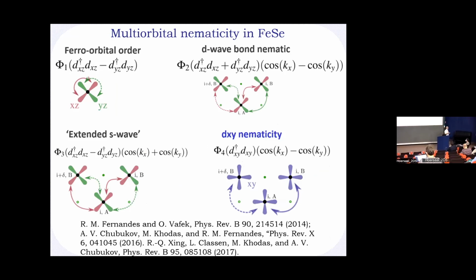Now, it turns out that in order to describe it, of course, you always break a B1G symmetry, but you actually need a combination of the nematic order parameters in order to correctly describe the resulting Fermi surface. So by symmetry, you have a ferroorbital order, which basically just splits the position of the XZ and the YZ orbitals. You have a D-wave bond nematic order, which is, let's say, an S-wave form factor, but cosine kx minus cosine ky, which is visualized here.